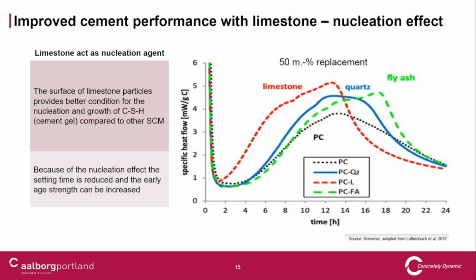Putting in quartz or fly ash doesn't change things much, but putting in limestone moves everything to a faster reaction — that's the nucleation effect of limestone. This is also used by some admixture producers in new accelerators, where they use nanosilicate or nano calcium hydroxide particles to accelerate concrete. This isn't a nanoparticle, but at least it's a fine small particle which acts in the same way as a nucleation site for the chemical reaction. So this effect we will see in our cement.